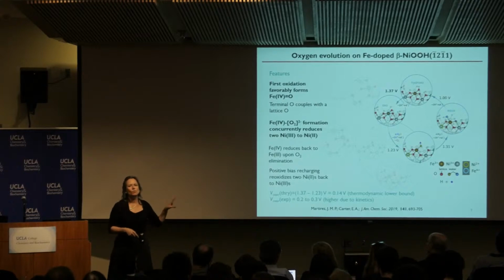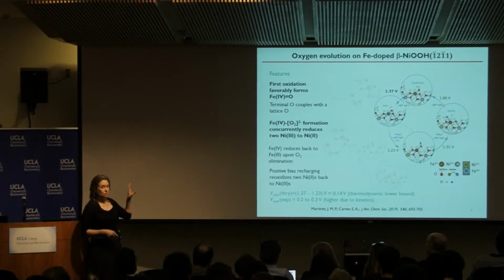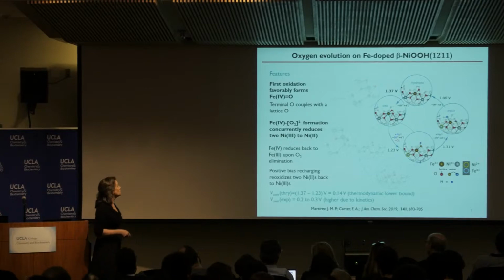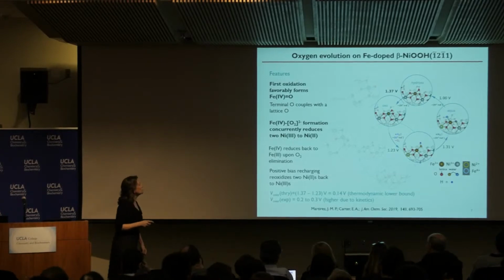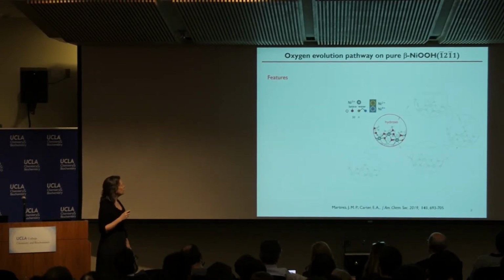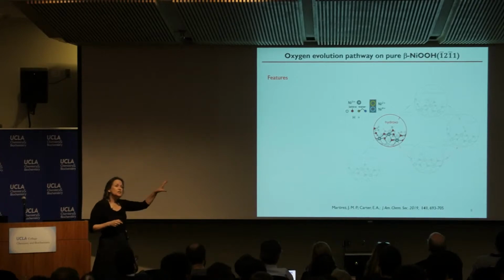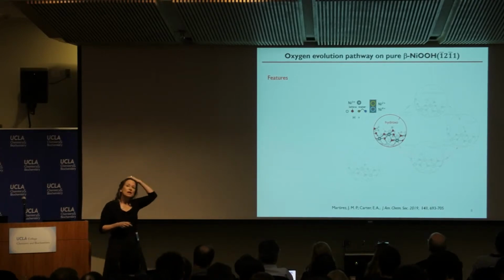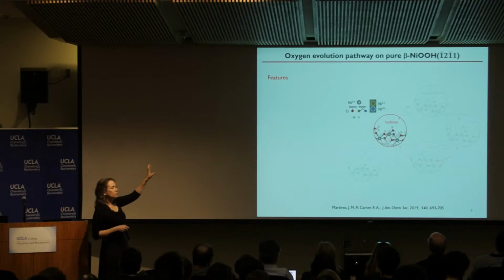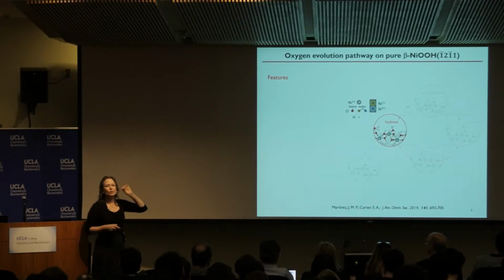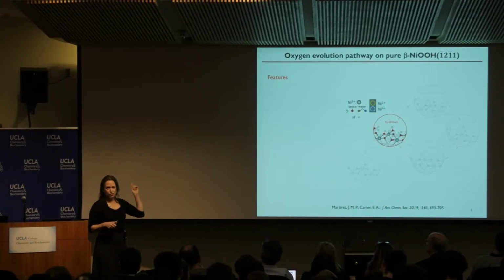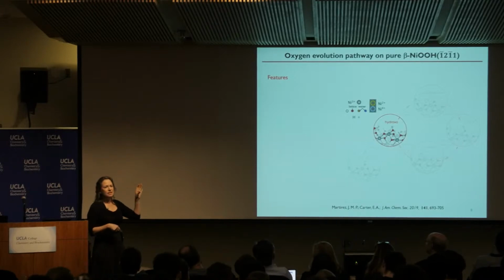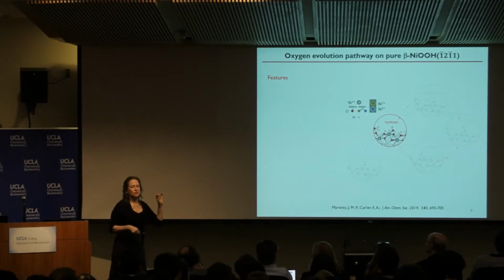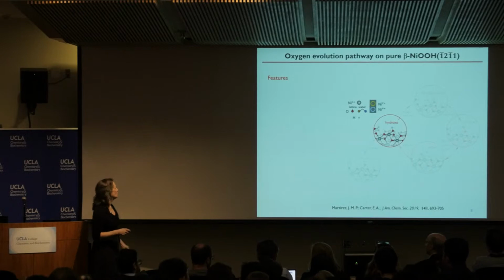It has to be that what the theory produces has to be lower than what's measured experimentally. So this is one reason why we believe that this particular kind of active site is really critical to do this kind of work, this kind of conversion. Contrast this to what happens without the iron. So here, this is the pure nickel. It was known that iron doped, as I showed you, is the best catalyst, and without the iron, it's much less efficient. So that means the overpotential is much larger.